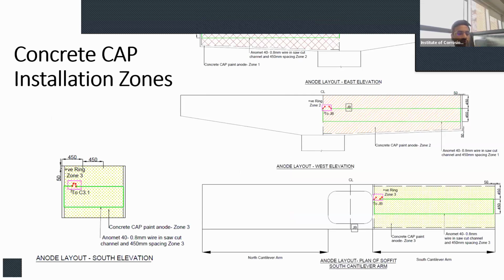Generally, for the zoning part, what we do is divide the zones depending upon the exposure of the structure. In general, the idea is to meet the current density demand, the local cathodic current density demand. Typically, zones for an impressed current system will have a current rating of about 0.5 to 2 amperes, or even up to 5 amperes for structures where the steel reinforcement distribution within the zone is uniform. As long as the reinforcement within the zone is uniform, we can go up to 5 amperes of current rating per zone.